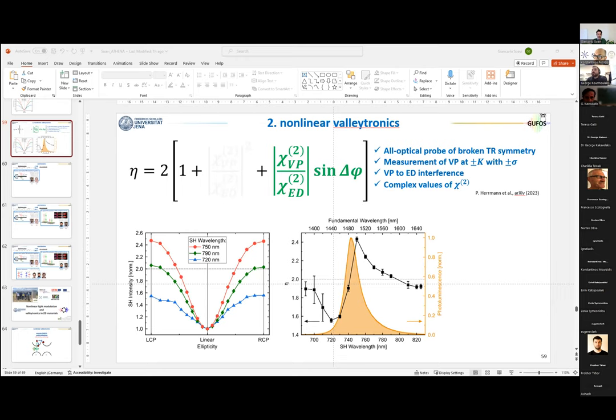I mean, there is no measure, except for this one, that is the only one that I know. We have no measurements from which we can retrieve the real and imaginary part of the, let's say, susceptibility coming from the valley. And I think this is somehow the difficulty in understanding this. So the next step would be first to characterize perfectly the intrinsic response, real and imaginary part. And then from this graph, we can derive the valley polarization refractive index. But we didn't go that far. It's challenging.